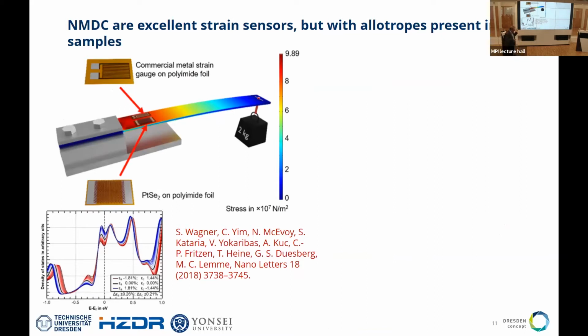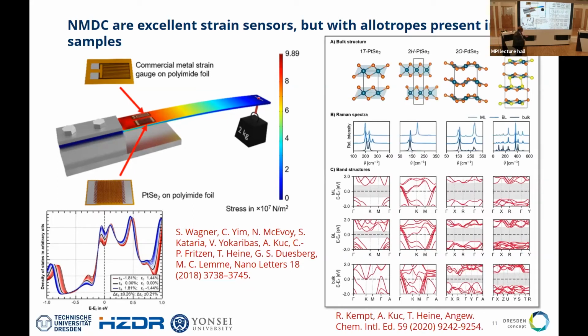strain sensor. So we collaborated here with Max Lemme and Georg Duesberg, and they were building this nice device here, right? And you can actually measure strain at remarkable precision here. The reason for that is simply that at the Fermi level, when you're straining platinum diselenide, you're changing the density of states very significantly. It's a very, very simple explanation for that. We got a project on that, we moved on, and we got a lot of difficulties from experiments. The reason for that was that it's very hard actually to get the very clean phase of platinum diselenide.